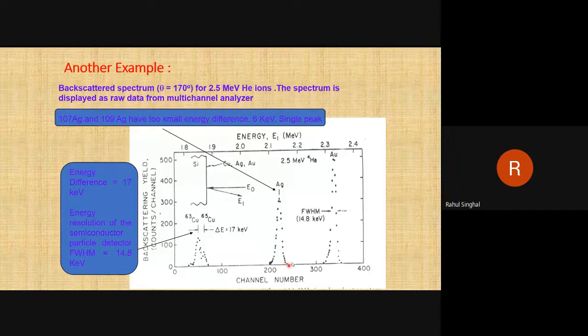But for the silver, you can see we are getting a single peak, while for the copper it's a double peak. We are getting two peaks, which you can deconvolute. Why? Because, as I have written here, for silver we have 107 Ag and 109 Ag, which have a small energy difference.